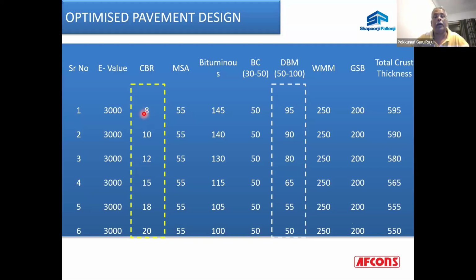So the idea is, if you are able to handle your soil parameters, and if you are able to freeze your subgrade CBR to say 15 by any chance, then what is magical is you can always play with your asphalt layer, and you can reduce your DBM up to 65 instead of 95. That means there is a reduction of straight away 30 millimeters in the construction of the asphalt road.